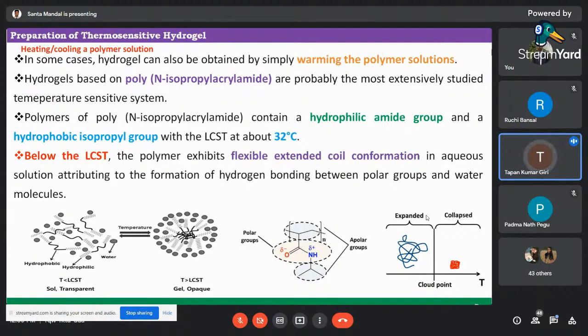Two groups are there. One is the hydrophilic amide group, as I have told previously, and another is the hydrophobic isopropyl group. So below the LCST, at 32 degrees centigrade, there is a hydrogen bonding interaction between water and the amide group, and that is soluble. But above the LCST, there is a weakening of the hydrogen bond between water and the amide group of the polymer. But the isopropyl groups of the polymer associate strongly, and that hydrophobic attraction or association is stronger. Ultimately, the water is expelled from the polymeric system and converted into the gel or hydrogel system. And in this way, the thermosensitive hydrogel systems are prepared.